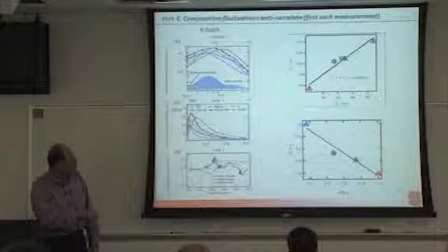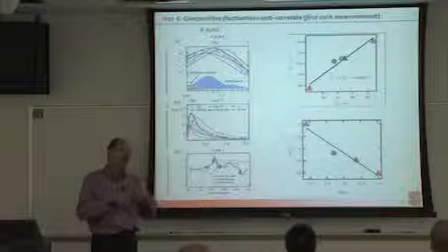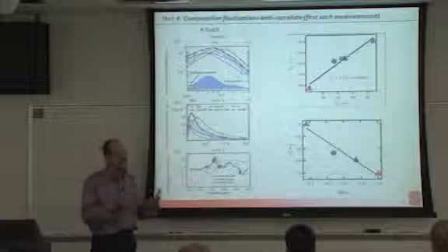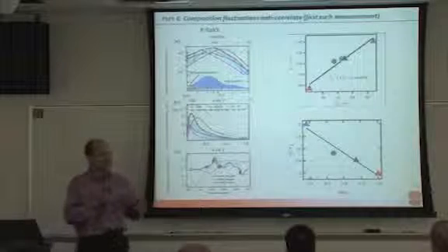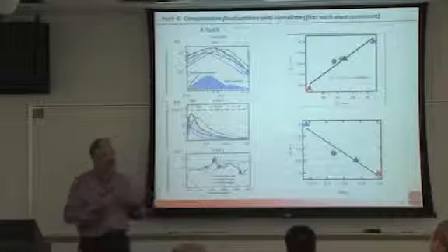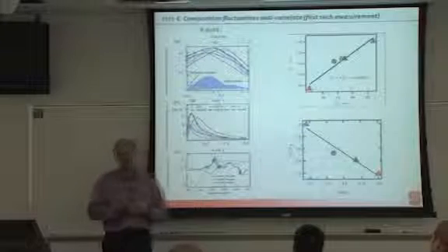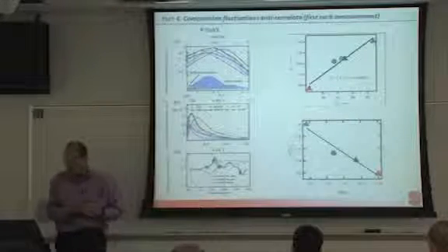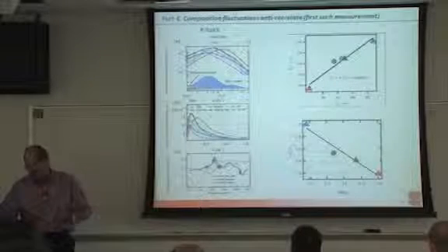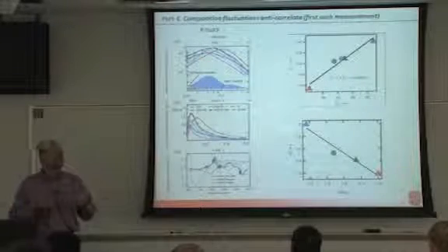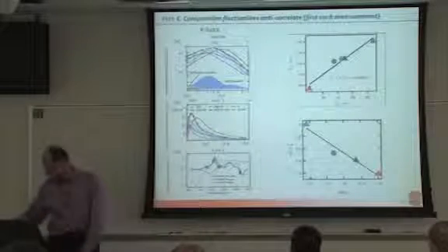And the small and large domains have an anti-correlated composition fluctuation. And that's also interesting. It makes sense as I draw material out of a nanophase into the macrophase. I'm changing the relative composition fluctuations that I'm measuring. So that's the first time that these details of a 3-phase system, which is implied by these measurements, could be measured. And this is work in progress.